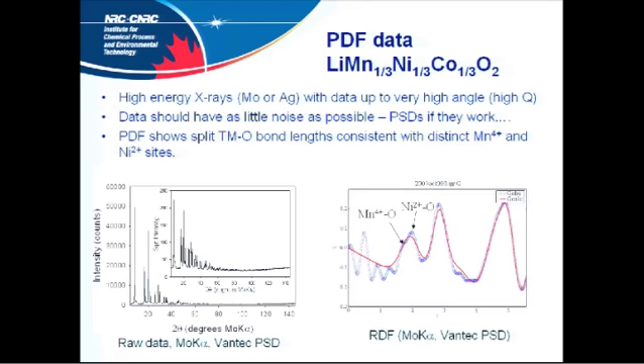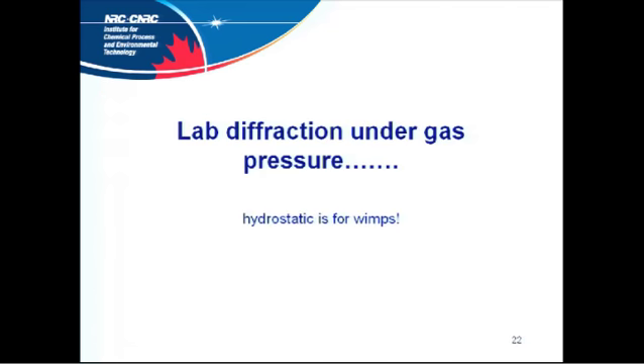Cover that. And obviously, the resolution of the pair distribution function is not going to be wonderful, but it's good enough to show you. This is a model of the random distribution, and this is the experimental data in the back, and you can see it splits. So basically all I've done here is only replicate what has been done previously on a synchrotron, so this is already known, but you can replicate it in a laboratory system. The data is not going to be as good, but you can do it.